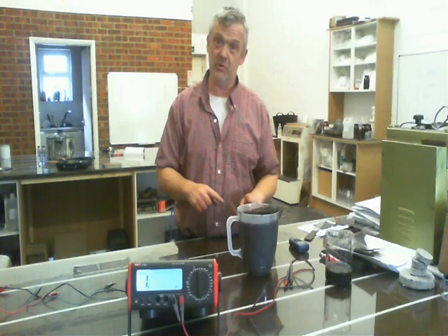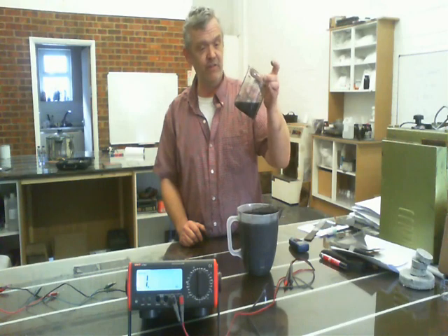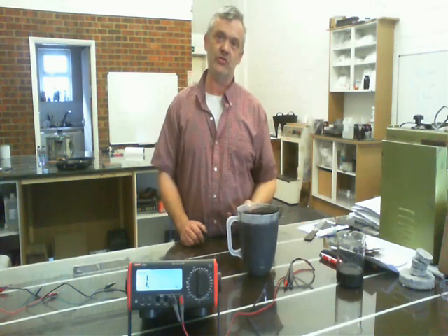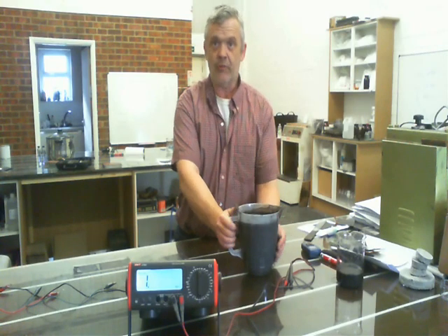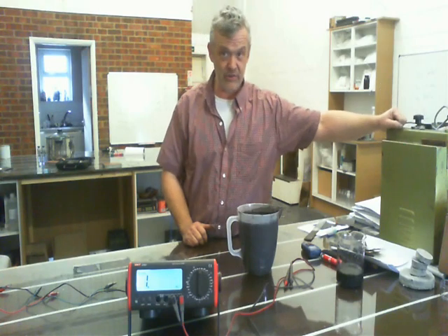Now the extra work I did was to put some graphene in there. I make all my own graphene — this is it, it's a fairly concentrated solution, about 5 grams per litre, so it's pretty concentrated. I make it all for my own use because it all goes into the inks. I used that on this ink, made up a litre and a half of this flexible rubber ink, and then put it through the three-roll mill, which is this thing here.